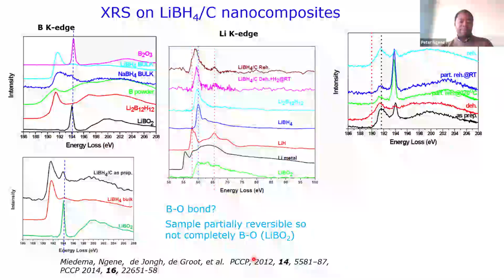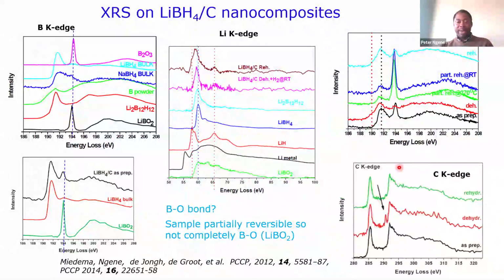And of course, this is what most of the referees said during that time. But we knew it was not completely a B-O bond, because our sample, we can partially hydrogenate the sample. So we do know if you have this lithium borate, then your sample will not be able to absorb hydrogen again, because this material is just a thermodynamic sink.